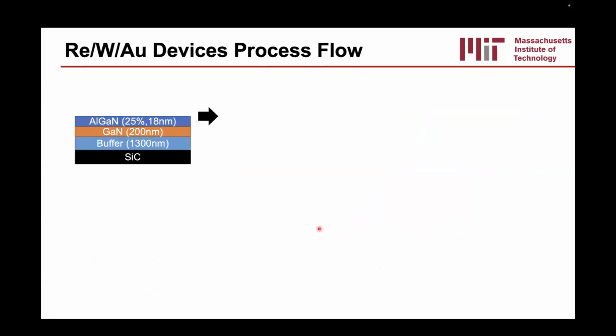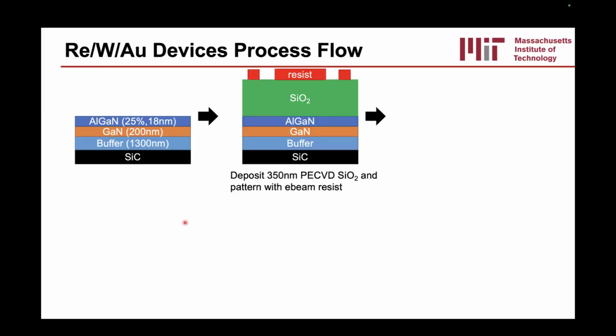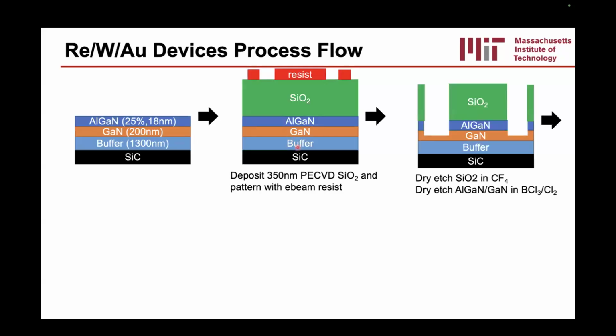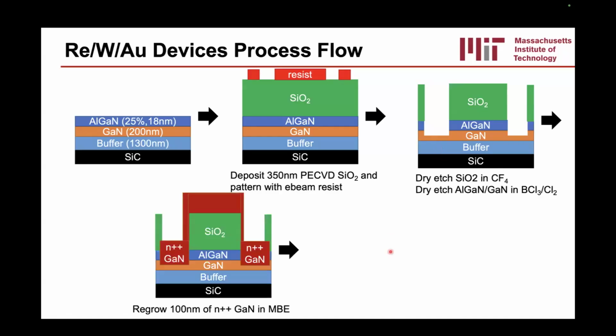All right, so now that we have all that, we can actually start our high temperature refractory gate process. This time we started with 25% AlGaN, 18 nanometers thick, on a silicon carbide substrate. We did a regrown process this time for the ohmics. We deposited oxide, etched the oxide in fluorine, etched the GaN in chlorine, and then we can send it to our MBE friends at OSU, and they can grow some really nice N++ silicon doped GaN for those ohmic contacts.